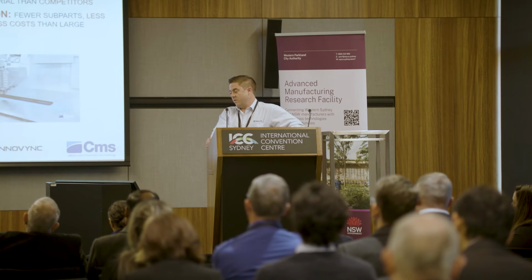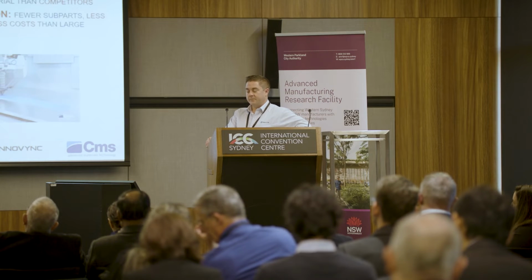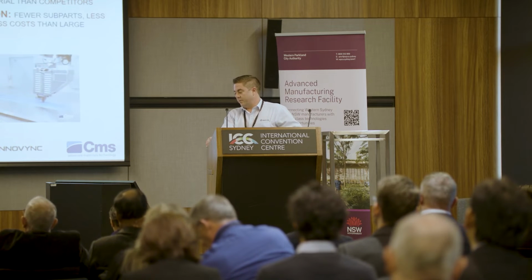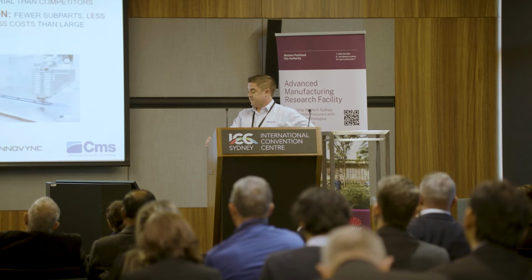The 4 parts manufactured in the typical method required 26 hours of printing, whereas the Creator took only 2 hours of 3D printing and 3 hours of milling. Also, in the context of epoxy or similar tooling board replacement, we've seen a raw material cost saving higher than a factor of 5 due to the hollow nature of the 3D printed parts.